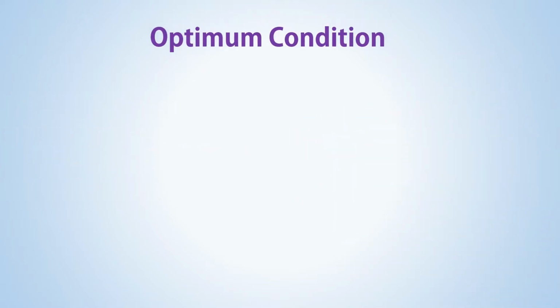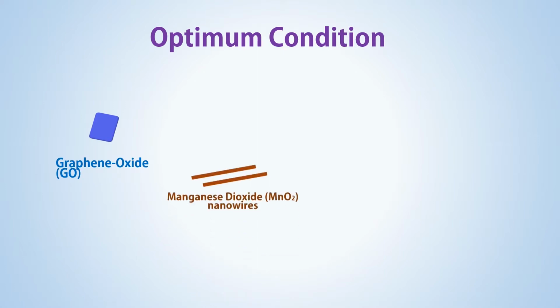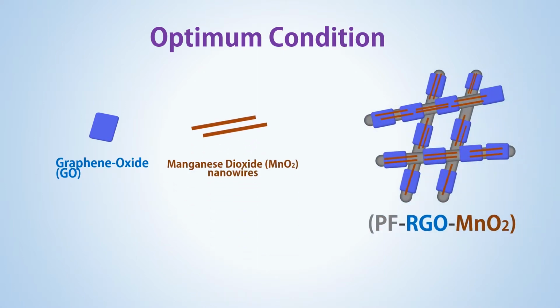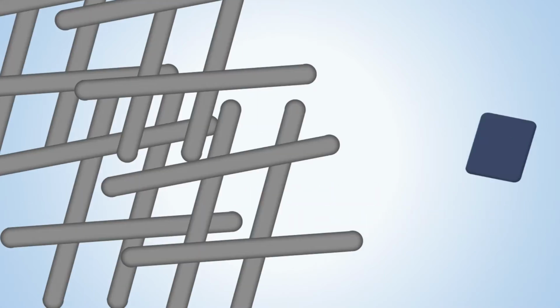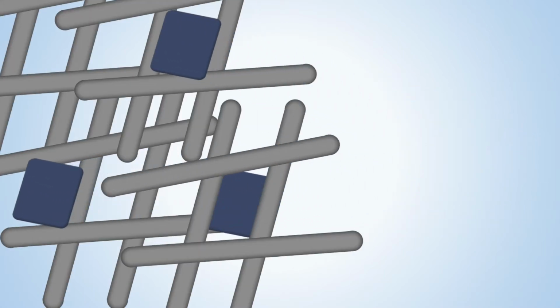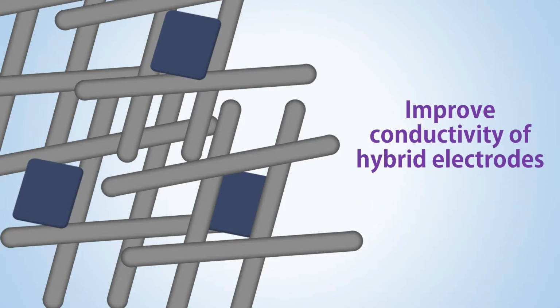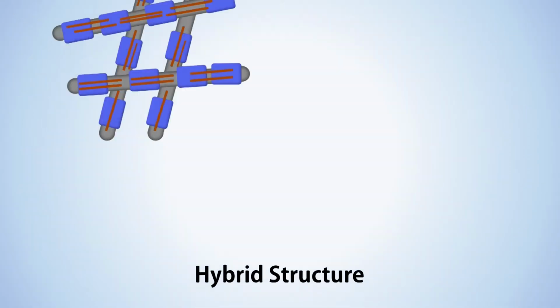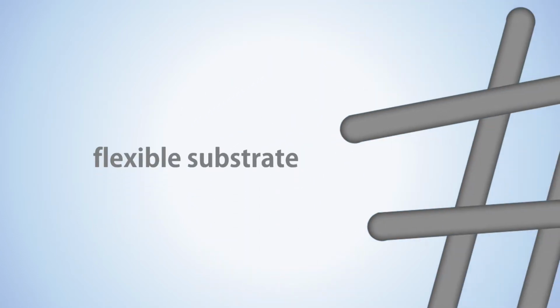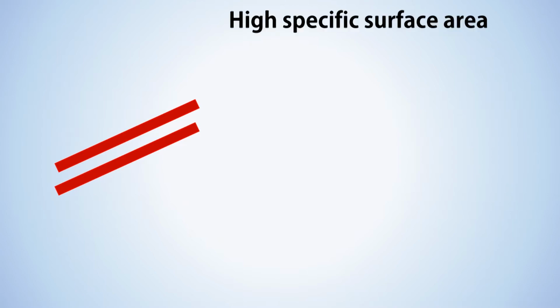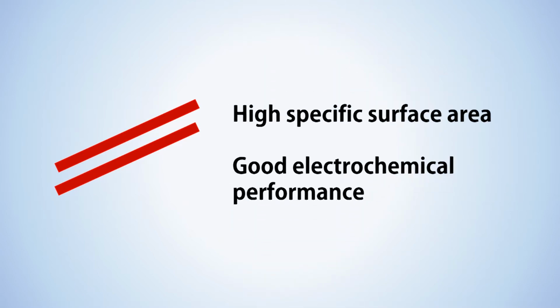There are optimum conditions for these mechanisms to occur. GO and MnO2 in the PFRGO MnO2 composites are fixed at 24 weight percent and 20 weight percent respectively. RGO sheets also fill the voids between the paper fibers, which is beneficial to further improve the conductivity of the hybrid electrodes. In this hybrid structure, the PF provides the flexible substrate. The MnO2 nanowires endow the electrodes with high specific surface area and good electrochemical performance.